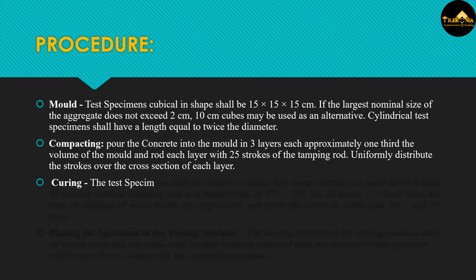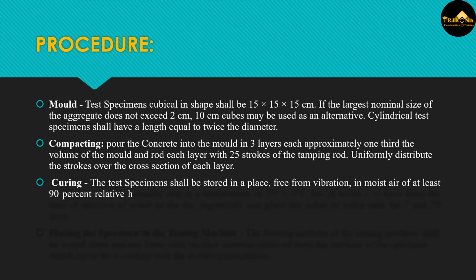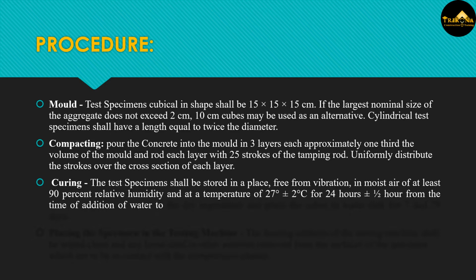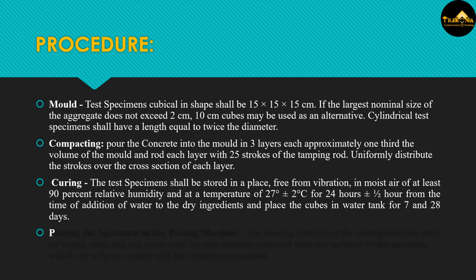Curing. The test specimens shall be stored in a place, free from vibration, in moist air of at least 90% relative humidity and at a temperature of 27 degrees ± 2 degrees Celsius for 24 hours ± ½ hour from the time of addition of water to the dry ingredients, and then the cubes are placed in a water tank for 7 and 28 days. Placing the specimen in the testing machine.